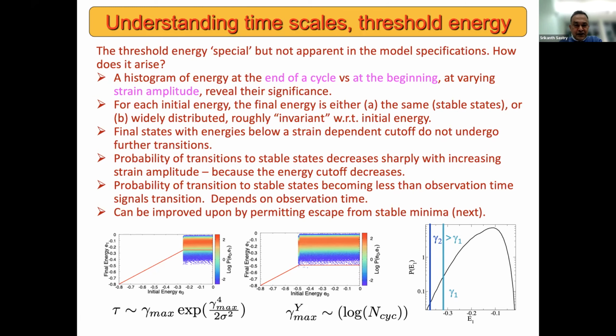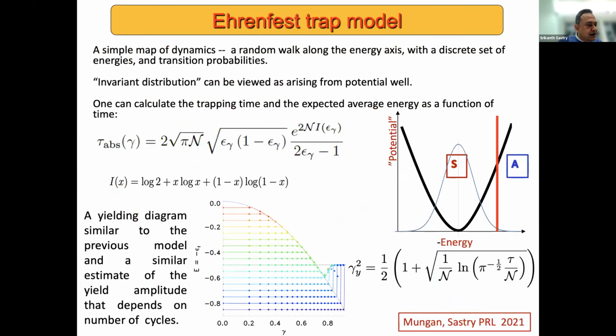which is stable with respect to the next cycle of deformation. I can then turn it around and say, if I've applied a certain number of cycles of deformation, what is my amplitude of strain beyond which I have yielding? And this is basically related to this number of cycles, or the time that I've observed the system for. And so I get an estimate for an observation time dependent yield amplitude, which is a fairly slow function of the number of cycles. But one can actually do better, as I will explain in a minute.